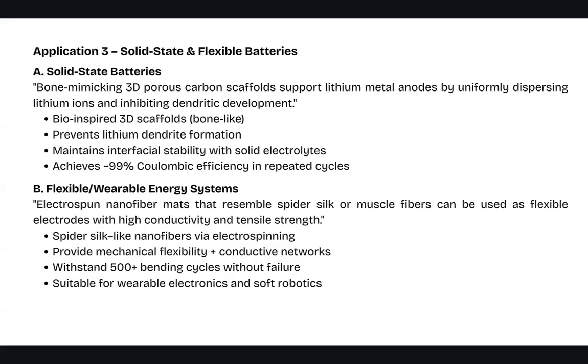The third application of bio-inspired electrodes is on solid-state and flexible batteries. In a solid-state battery, a bone-mimicking 3D porous carbon scaffold supports the lithium metal anode by uniformly distributing lithium ions and inhibiting dendrite development. Bio-inspired 3D scaffolds like bone-like structures prevent lithium dendrite formation and maintain interfacial stability with the solid electrolyte, and the architecture also achieves 99% Coulombic efficiency in repeated cycles.